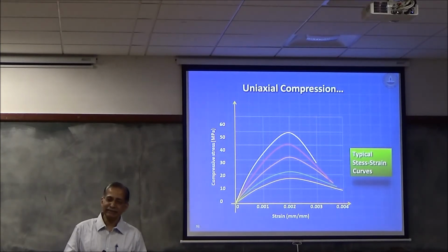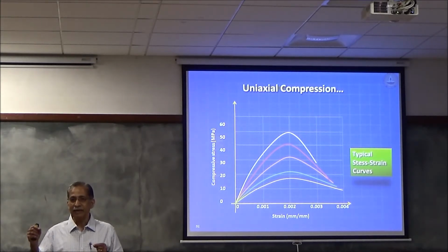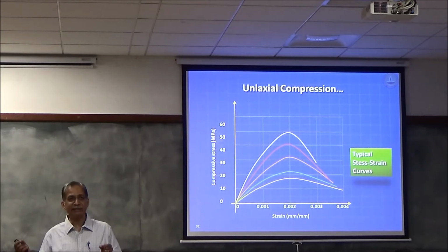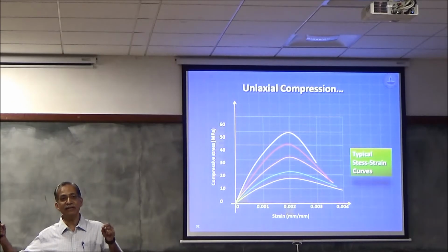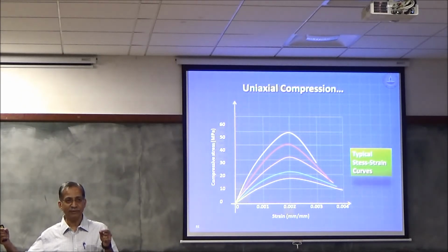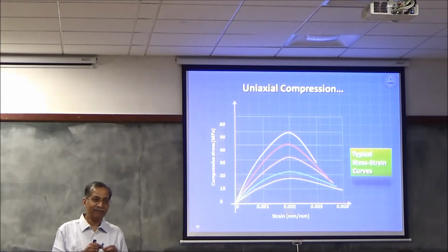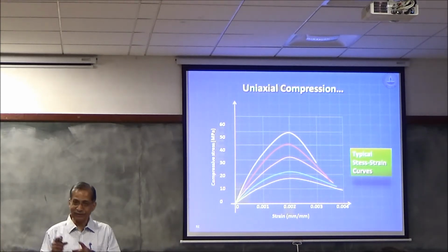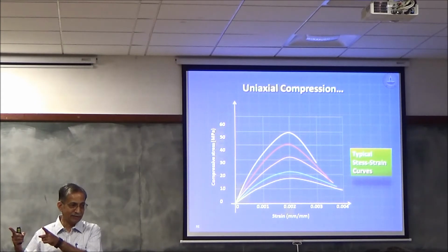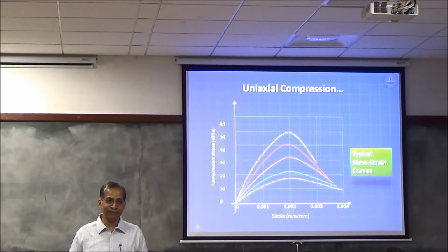Well, all I want to say is that it's been experimentally proved that when there's a strain gradient, you get more or less the same stress-strain curve, but you'll find that you get a larger failure strain. This is experimentally proved. That's why in the IS code, in other codes, we have a failure strain as high as 0.0035 when you have bending. But in compression, we don't rely on the post-peak strain. We limit it to 0.002. But otherwise, we use the same stress-strain curve. Got it?